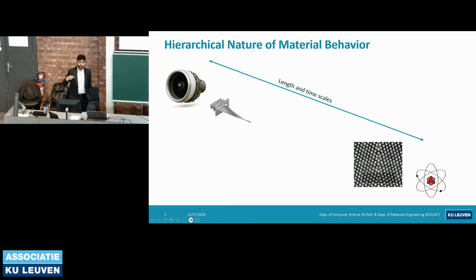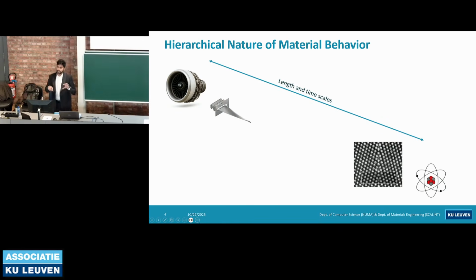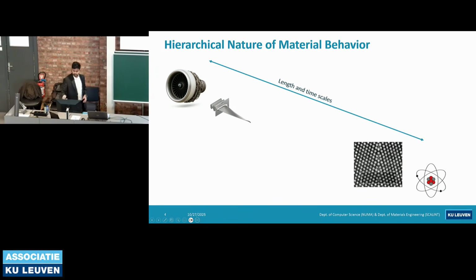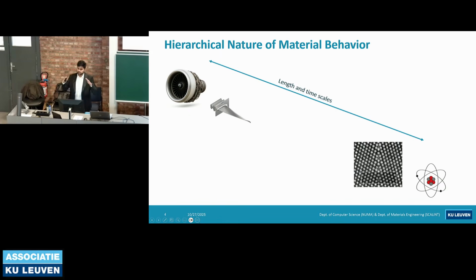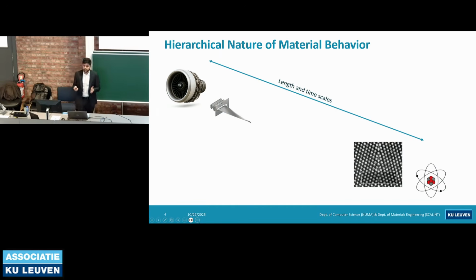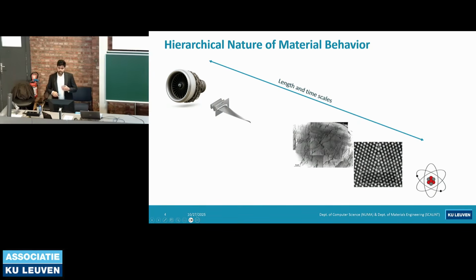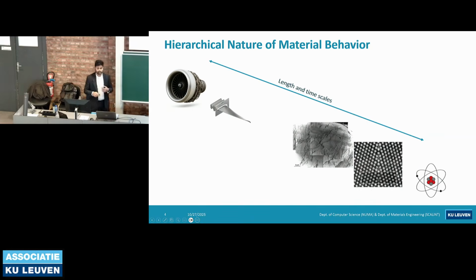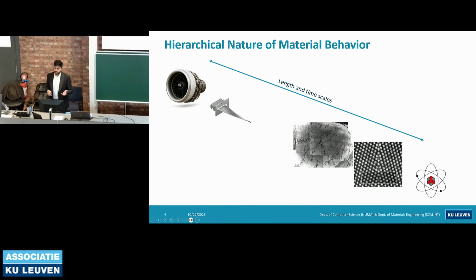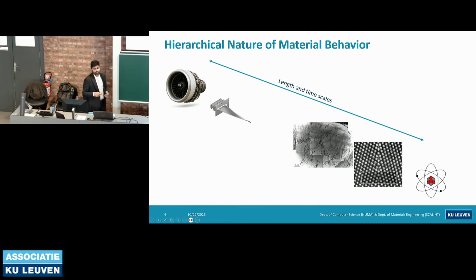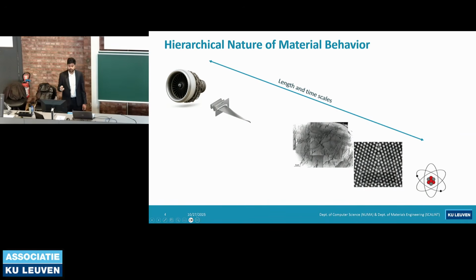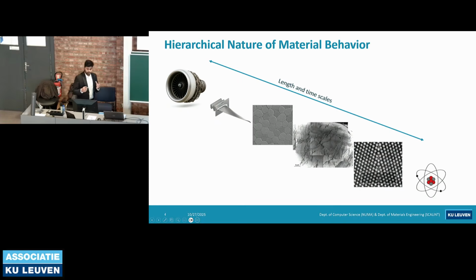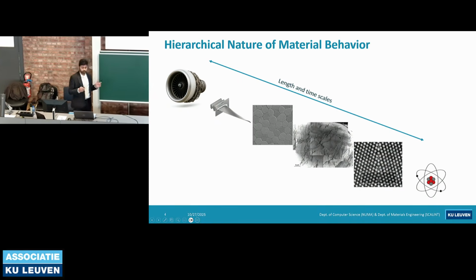As you could see here, if you have a molten metal and you solidify it, these atoms start stacking together in an organized way at a nucleation point. Now, the condition at one nucleation point is different from another, and that is why you could see that there's a boundary between the two crystals. These are called grain boundaries, and the regions between these grain boundaries are grains. Now, the stacking of atoms is usually not flawless, which is why you have defects. These defects, especially dislocations at microscale, form the fundamental mechanism of deformation. If these defects were not present, then metals would not deform but simply shatter like glass. And these individual grains together form the polycrystalline structure of a turbine blade that you could see here.